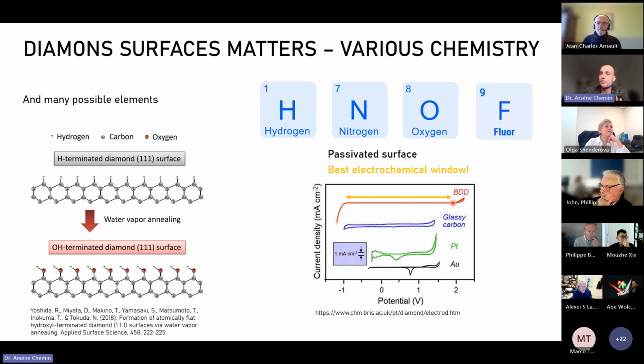So it makes boron-doped diamond electrodes a very good substrate in order to understand and probe the electrocatalytic properties of other materials on top of it. It also has very little capacitive behavior. If you look at the glassy carbon here, you can see that the cycle is slightly open. That basically means there is some capacitive behavior at the surface and at the interface that you barely see on boron-doped diamond. So diamond is actually great for catalysis. Very bad for creating hydrogen, unfortunately, because it's completely passive, but very good for probing other materials.